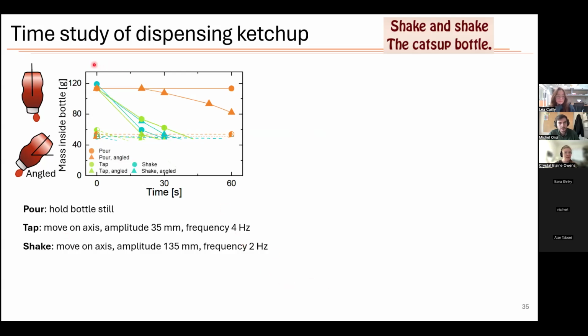And so here, if we start with a higher initial mass, you can see that the ketchup starts flowing quite a bit faster for both of these cases. And if we start with a lower mass, it also starts flowing faster. But for all of these cases, we found that we reach something that we call a residue threshold, where no matter how you shake or how you pour or what angle or what frequency you use, you're going to always have just a little bit of residue left inside the bottle.